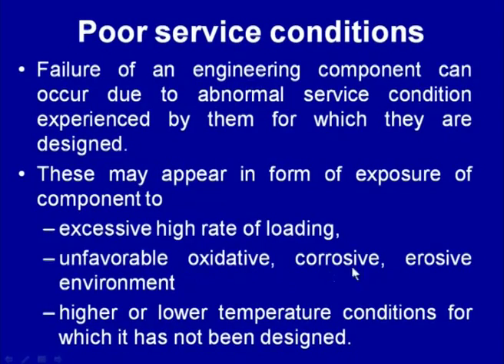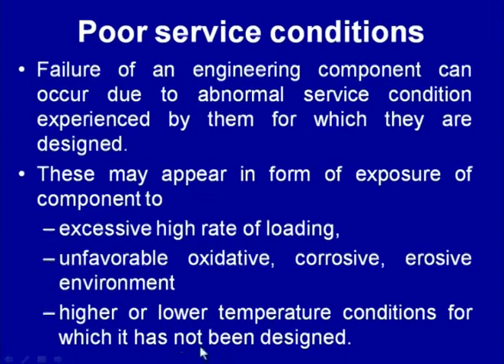So, the exposure of the component to abnormal service conditions can promote the failure of the component due to poor service conditions. These may be in the form of an excessively high rate of loading, leading to embrittlement of the component; unfavorable oxidative, corrosive and erosive environments, leading to degradation of the material dimensions over a period of time and developing stress ranges on the surface of the component; or exposure of the component to excessively high or low temperature conditions for which it has not been designed.